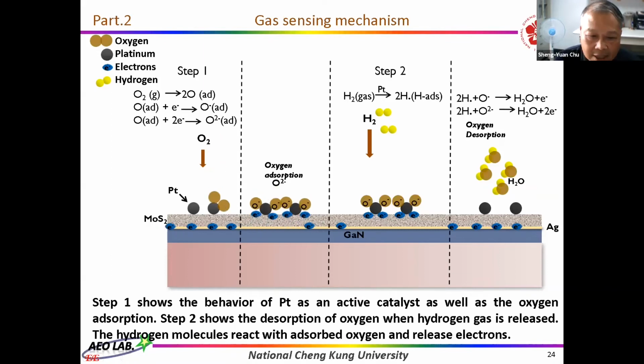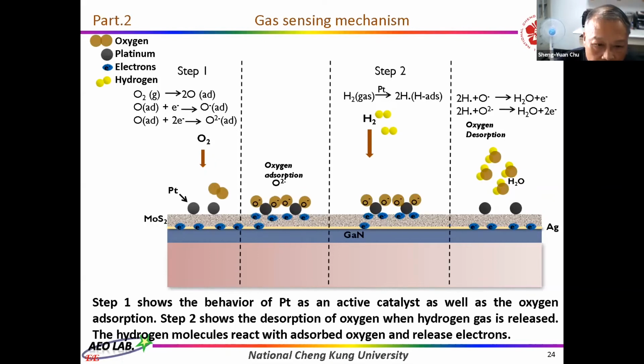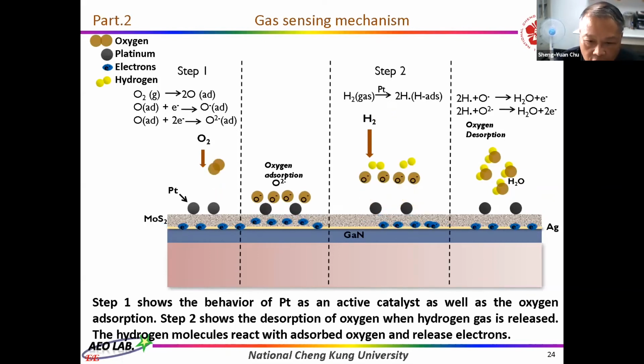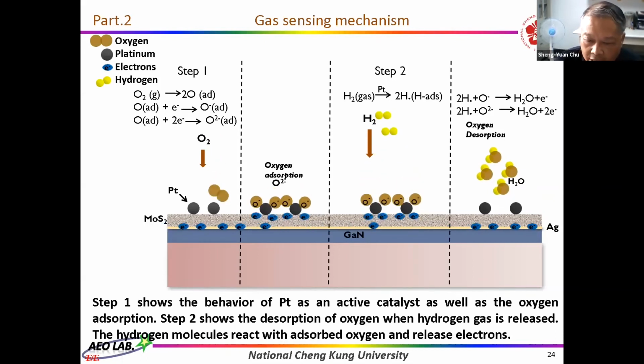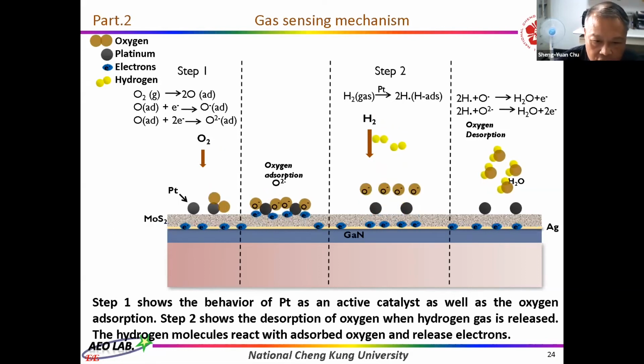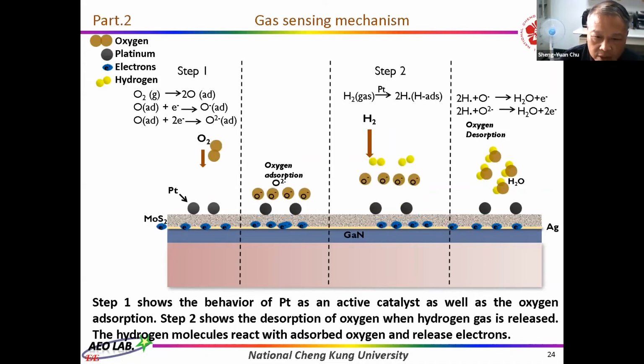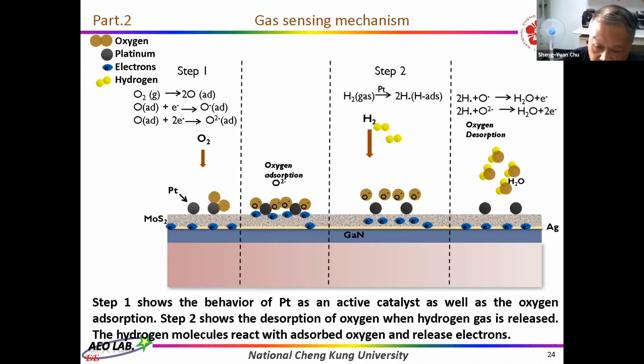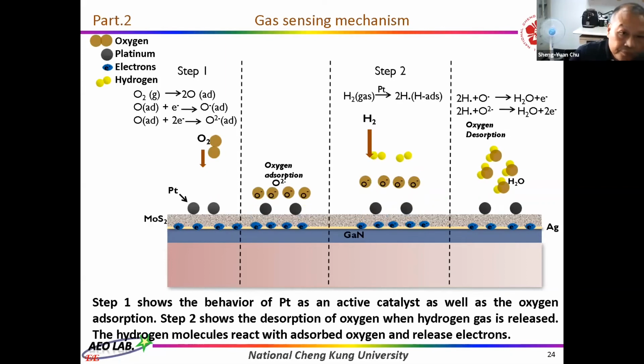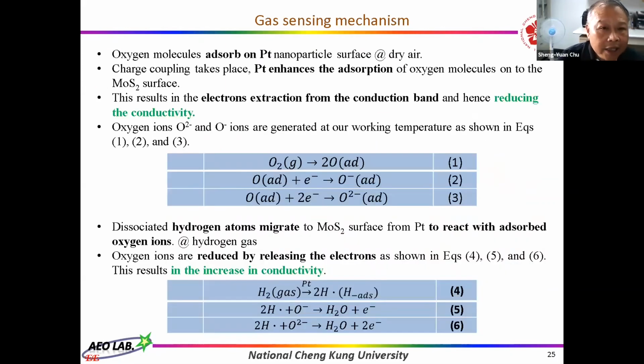as well as the oxygen absorption. And also in step 2, it shows the desorption of oxygen when hydrogen gas is released. The hydrogen molecules will react with absorbed oxygen and release electrons. And the detailed mechanism is shown here. Oxygen molecules are absorbed on the Pt nanoparticle surface during the dry air, and the charge coupling takes place.